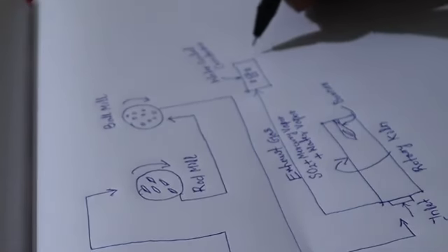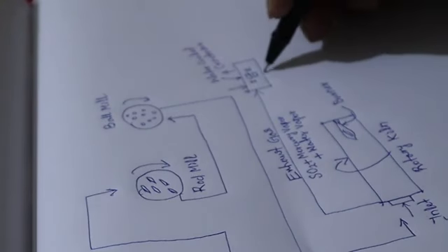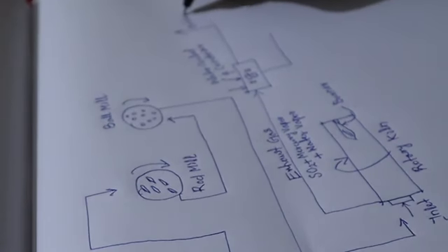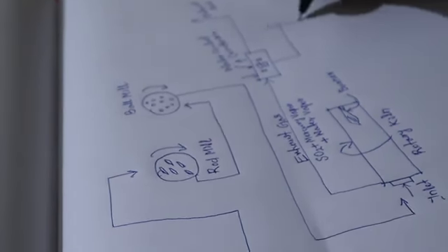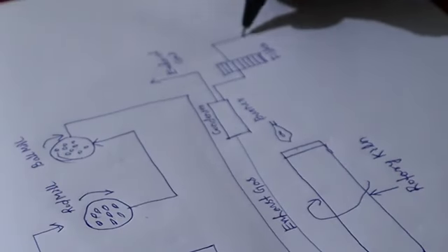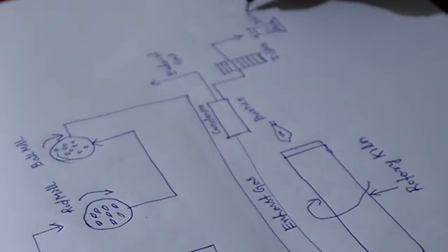Mercury, which has a boiling point of 357 degrees Celsius, is the first to condense into liquid, leaving the other gases to be vented out. The impurities are removed by filtration, leaving a mercury that is about 99.9% pure and can be used directly from the roasting and condensing process. Higher purity can be obtained through several refining methods.